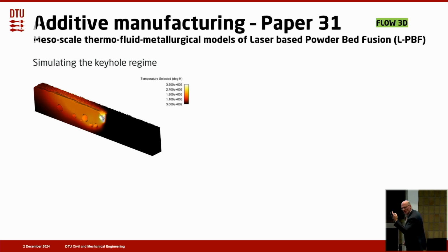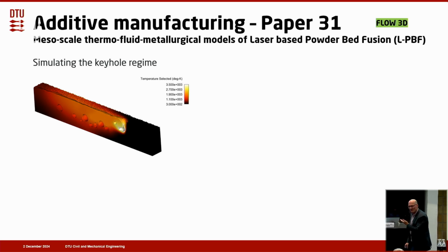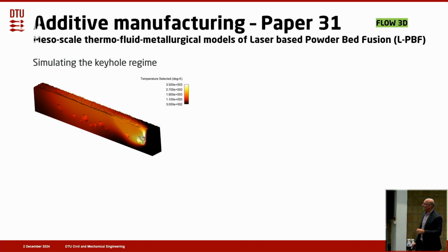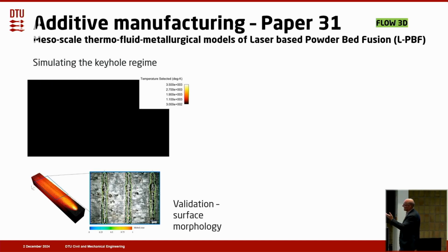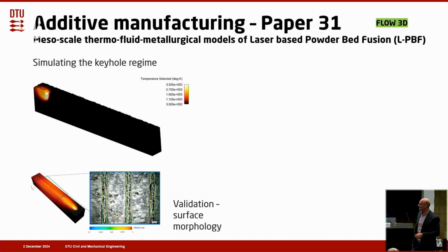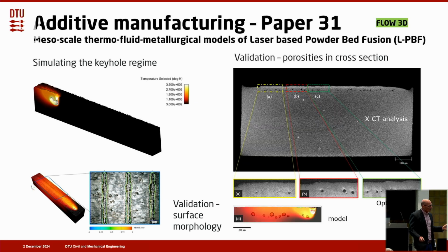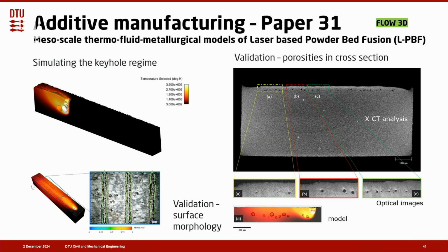And that bubble could go to the top due to buoyancy, or it could be frozen in by the advancing solidification front. And then you get porosities. And these porosities, we validated the predictions against the surface morphology, and we also validated against these XCT pictures here. And you could see that the model and the images showed, I would say, porosities of similar size and similar distribution and occurrence.